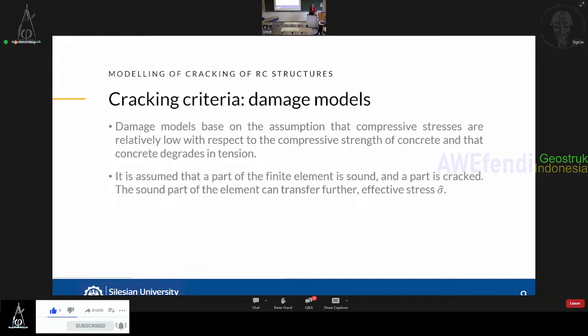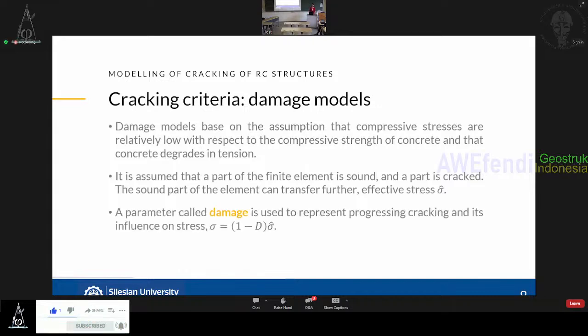So as I said, in such damage models, we assume that part of the element is sound, it is healthy, and part is cracked. And this healthy part is still able to transfer some residual stresses. And we are modeling this behavior with the use of the parameter which we call the damage. And this model has been fairly well described during the last presentation, but just to remind you, we have this damage parameter. So as you can see from this very simple formula, if the damage is 0, so the element is not cracked at all, then the element can transfer stresses fully. And when it is entirely damaged, it is no longer able to transfer stresses. Everything in between is a residual stress to be transferred.